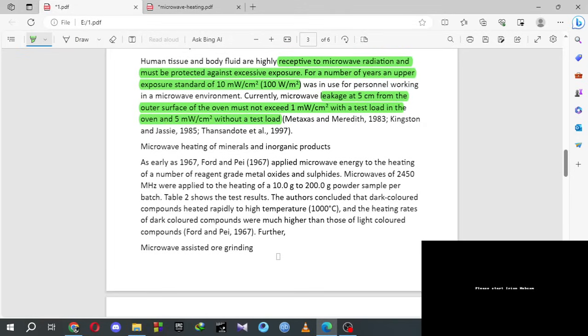Microwave heating of mineral and inorganic products. As early as 1967, Ford and Pei applied microwave energy to the heating of a number of reagent grade metal oxides and sulfides. Microwaves of 2450 MHz were applied to the heating of a 10 gram to 200 gram powder sample per batch. Based on the test results, the authors concluded that dark colored compounds heated rapidly to high temperature and heating rates of dark colored compounds were much higher than those of light colored compounds.